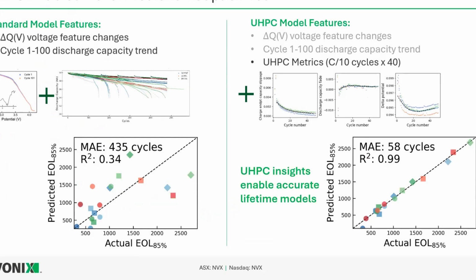Using standard model features like in the Severson model, using delta QV voltage feature changes, cycle 1 to 100 discharge capacity trends of cycle aging data, especially when we're using cells that have silicon, that don't have silicon, using high temperature, high voltage, high nickel cathodes, and then lower temperature and not using that part of the cathode. These models don't do a very good job at predicting lifetime.